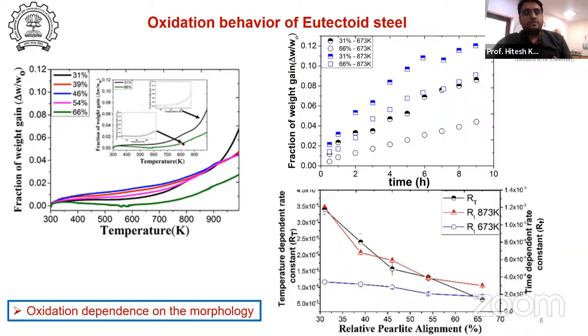Is it true for the isothermal situation also? Meaning when we put the material at a particular temperature for long hours. As I already discussed in steel, we divided the temperature into two different parts. One is a low temperature where only two phases are stable, and a high temperature where three phases of oxides are stable. So we chose 673 and 873. As you can see, when we are talking about 66% aligned, the material is getting less oxidized. So the material is becoming more resistant to oxidation.